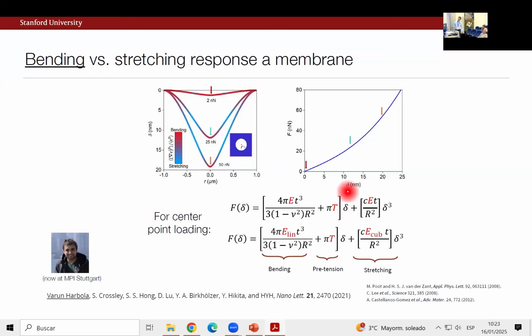And the details, this prefactor has various geometric things in it, right? So this is the Young's modulus. This is the pretension. So did you stretch the membrane before you put it on the drum head? Poisson ratio, and geometric factors. Okay? The interesting point of this is that if we go to this stretching versus bending regime, we'll induce kind of a nonlinear response in this force deflection curve. Okay? And again, if I have a simple linear elastic medium, again, similar factors, it'll be the same Young's modulus.